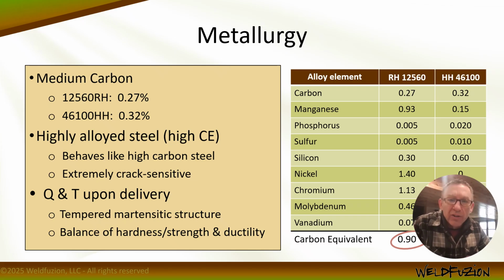And these things are delivered as a tempered martensite structure. And as you know, or all welding folks know, when they learn about steels and steel metallurgy, when we heat a material into the austenitizing range and we quench it down to room temperature really, really rapidly, we're trying to form martensite. And once you have enough carbon or alloying content, that rapid cooling tends to form the hard, brittle microstructure that's definitely got wear resistance, but it doesn't have a whole lot of ductility. So by retempering that, we can restore some of the ductility to the material while retaining the strength and the hardness of the martensite. So that's really the trick behind what we're trying to preserve with welding, is balancing the hardness and strength with that ductility so that we can ensure that it fails in the way that it was designed.